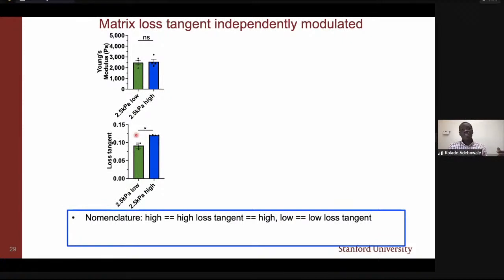So this strategy that I described in the previous slide allows us to make alginate collagen materials that, for example, have an initial Young's modulus of about 2.5 kilopascal. Importantly, however, these materials have different loss tangent values, as shown by the graph on the bottom left. And for this part of the talk, I'll use a nomenclature where high would refer to a high loss tangent material. So that's the graph in blue on this slide.